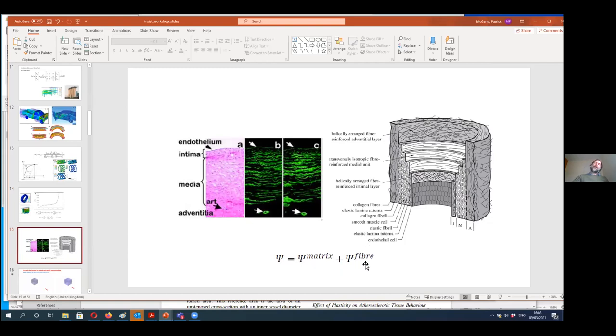Now, because blood clots also have fibers in them, usually a fibrin network rather than a collagen network like we get in an artery, we felt that we could use a similar strategy for blood clots. We would basically decompose the blood clot into a matrix part, which represents things like red blood cells or the non-fibrous parts of the clot, and then the fibrin network.